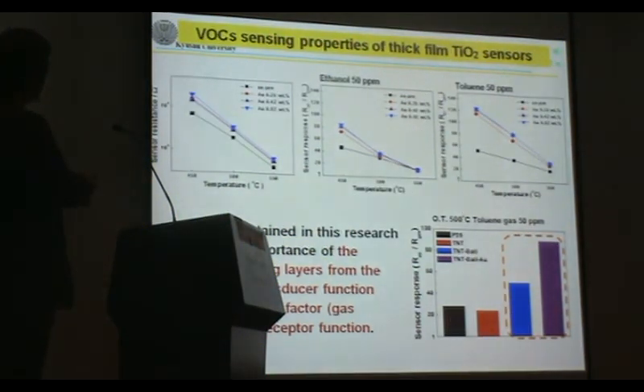Finally, this sensor shows a very good sensing property. Usually the nanoparticles of TiO2 didn't show high sensitivity like this, but this nanotube shows very high sensitivity, maybe increased by 4 times. So we can modify the sensitivity and the selectivity by controlling the receptor function, transducer function and the utility factor.